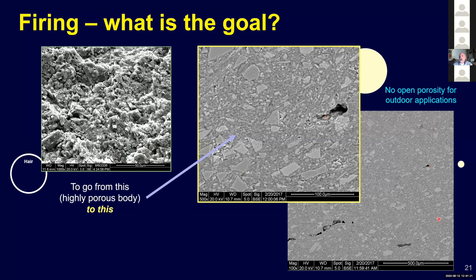So overall, this is an example in the lower right here of Boston Valley. It's much lower magnification, but you can see the uniformity of their microstructure. There's a couple spots of porosity which are not problematic because they are isolated spots and places of porosity. Also, the way that the material is loaded, which is typically in compression, those porous regions don't really make any difference. So a well-fired body has a microstructure similar to what you see in the center of the screen. It's very, very durable, and it gives terracotta its long-term durability and quality.